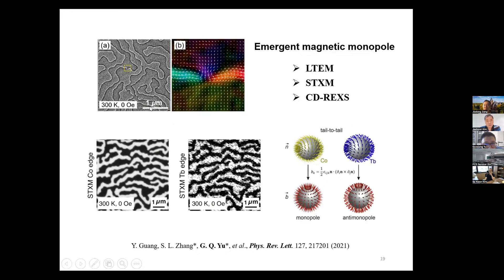In Lorentz TEM, what we can see is: looking here, there's a bright top and dark bottom on one side, and then the contrast reverses — for the right side the top is black and the bottom is white. That means the spin in the domain wall is pointing in different directions on each side. This is exactly the spin texture for the skyrmion domain wall containing a singularity. Combined with knowing the three-dimensional structure in the cross-section, we can confidently say there is a Bloch point somewhere inside. The emergent magnetic monopole exists randomly in this area, and we are thinking about how to control the creation of these monopoles — dynamics would be very interesting.